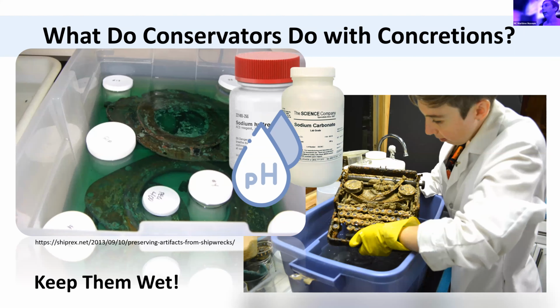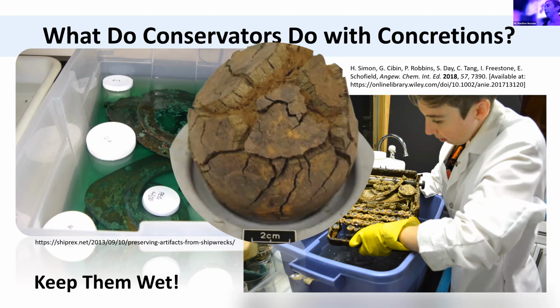So you might have organics or sometimes even modern materials like rubber or plastics, where all of a sudden moisture is being rapidly removed. So that can result in cracking or flaking or basically destruction of your artifact. And this is a rather famous example. This is a cannonball from the Mary Rose. So sometimes the concretions themselves fall apart. We have examples of that if they're misidentified and not placed wet. And you can also have problems even after they're deconcreted, where you have artifacts essentially falling apart from the inside out.